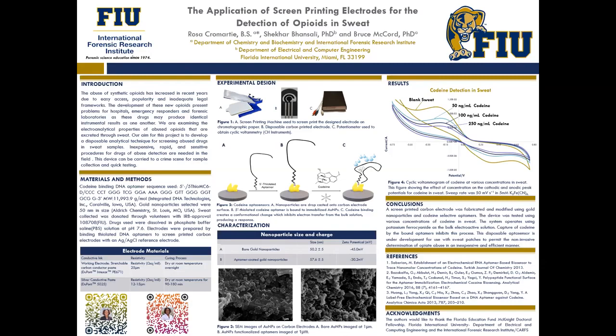And then in the presence of codeine inside of potassium ferrocyanide, we were able to electrochemically analyze the presence of codeine. So here you can see in part C of the schematic design that there's a switch-on assay that occurs. After binding with codeine analyte, the aptamer structure takes on a conformational change. This shows that during the electrochemical sensing process, there is the oxidation of ferrocyanide.